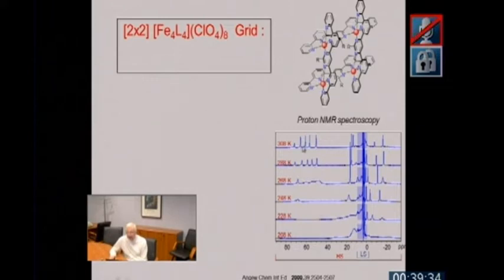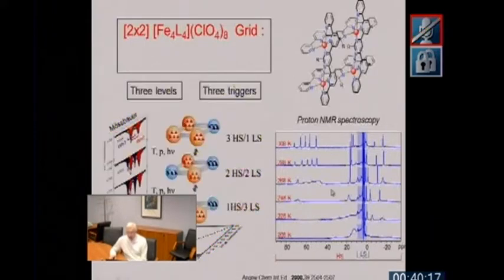In other words, it means that this grid has become paramagnetic. Furthermore, when you change the temperature, you see that the spectrum changes dramatically from very expanded, -20 to +80. It coalesces progressively as the temperature is lowered to generate a broad peak in the region here, which is the low spin region. That indicates that at the beginning, the complex was high spin. Some, or maybe all, of the iron centers have become high spin. And as you lower the temperature, they become low spin, and then all the bands merge together in this region.